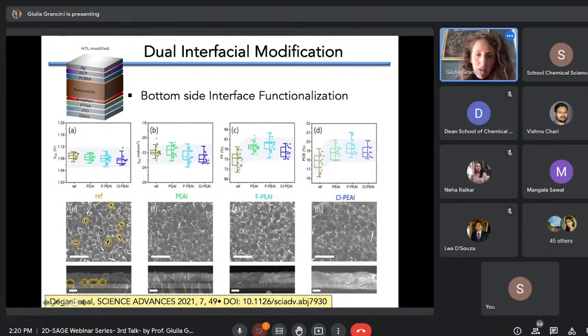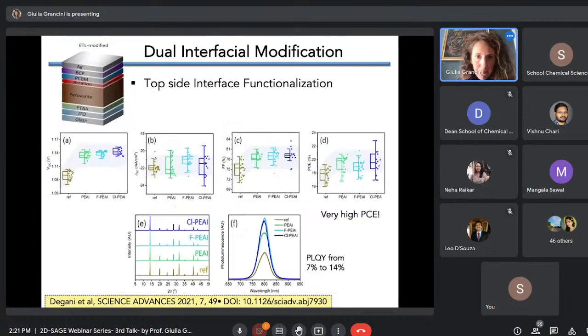So the crystal growth of the perovskite on top of the modified interfaces is much better, which gives you increased performances. So this is the reference. This is with the 2D passivation. You see the PCE improves, which is mainly related to an improvement in the fill factor, which translates in a better interface, better contact with the bottom interface.